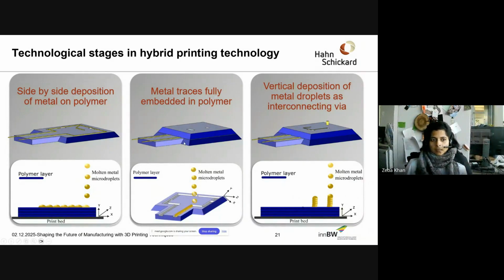The two traces coming out are something you can plug into a USB connector and then immediately verify that it works. In the next technological stage, we have embedding of these metal droplets. If we want to create three-dimensional structures, we want to embed these metal traces, which was also technologically challenging, because we have these bulk molten metal droplets printed on FFF polymers with deformation temperatures ranging from 56 degrees Celsius to 110 degrees Celsius. So we did some scientific assessment to see if we can print polymer channels, as you see here in this image, and deposit the droplets in those channels in a way that gives very low void formation around the channel and a low coefficient of variation in the width of the printed tracks.